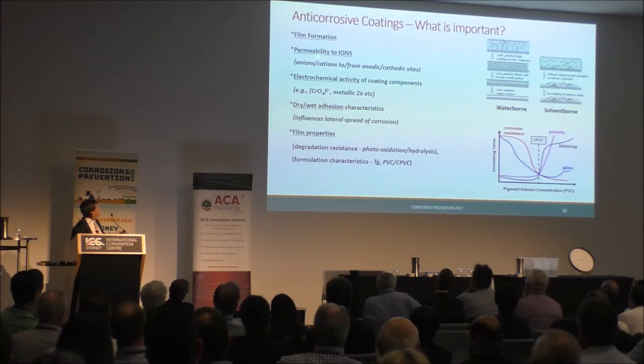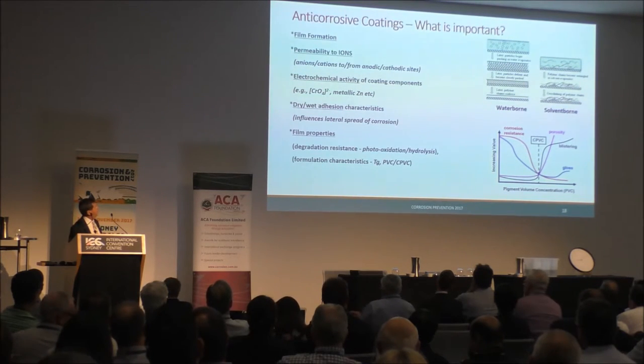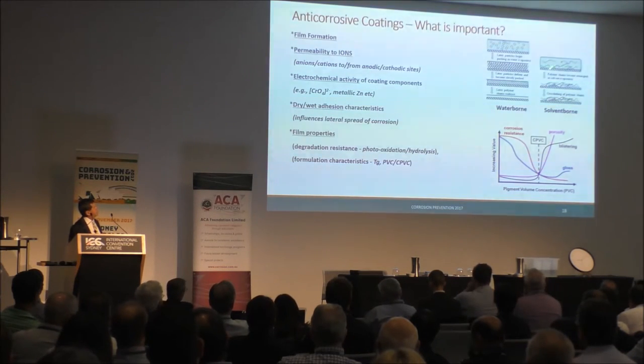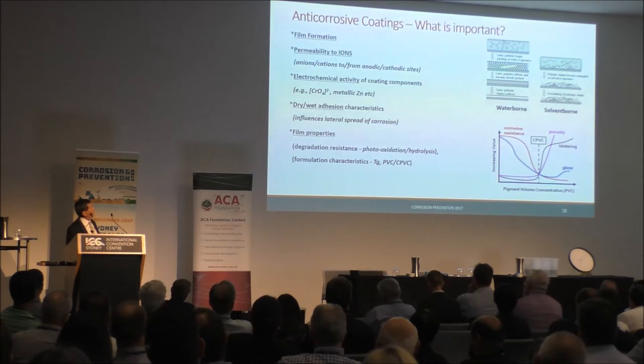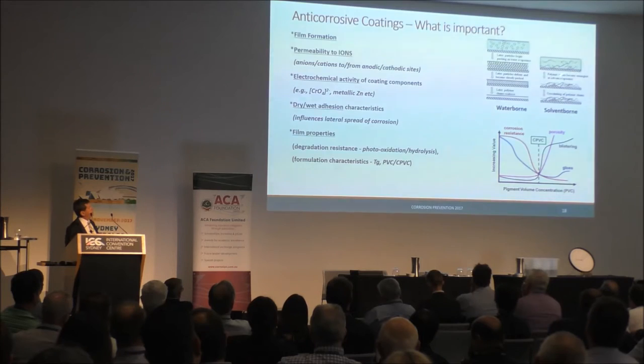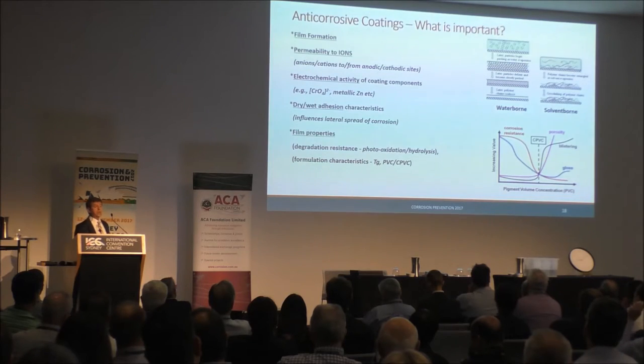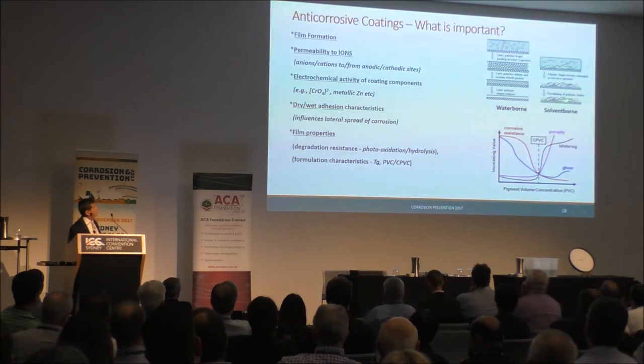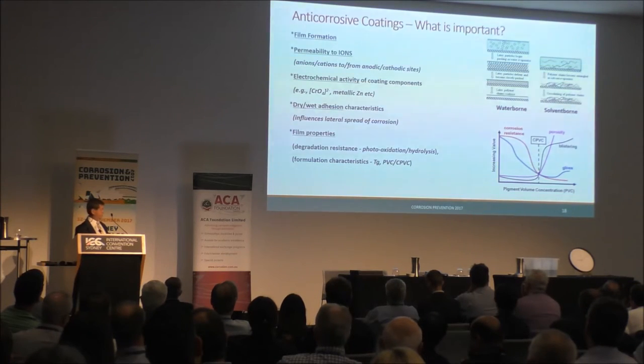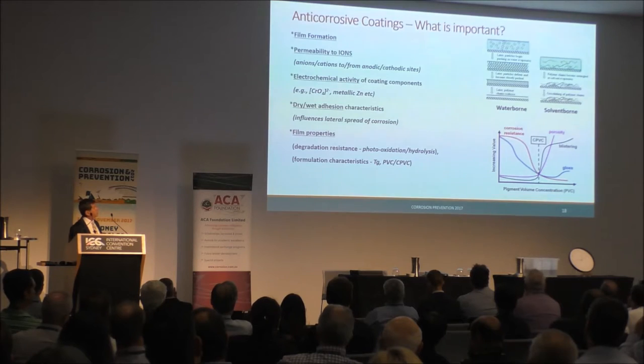Well, film formation is really a critical factor. When we look at the different resin systems that are designed, the synthetic resins I mentioned before, they really fall into two categories, waterborne systems and solvent-borne systems. In the case of solvent-borne systems, we put low molecular weight oligomers and polymers together in the presence of a solvent, plus pigments and other additives. The solvent and resin together, over time, will cure by solvent evaporation and allow these low molecular weight polymers and oligomers to react in place to form long chain polymeric systems, which are typically very impermeable to the passage of moisture and oxygen, to an extent.